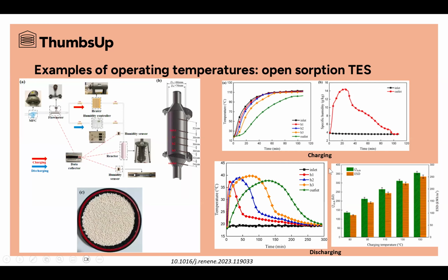Here is an example of operating temperature in our open sorption TES. We can see in this graph the charging phase. The range of temperature is between 110 Celsius degrees and 25 degrees during the charging phase. In this part of the graph, we can see the inlet humidity. It is constant at 4, and the outlet humidity is released by the water absorbed in the material. In the discharging phase, we can see this other range of temperature between 40 and 20, and this is the heating of this reaction.